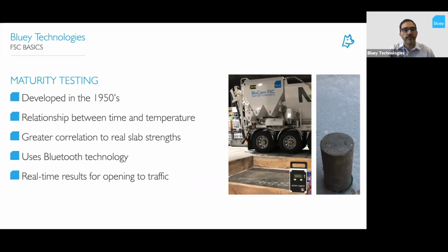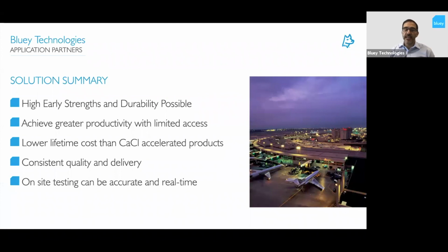So just in summary and finishing up, high early strengths and durability are possible, all in the one product. We can achieve greater productivity, even though we have limited access, by using fast set concrete and cement products. We have a lower lifetime cost than using a calcium chloride accelerated product, and we can now achieve very consistent quality and delivery, particularly with the backup of that on-site testing, which can be accurate and in real time. So a lot more reliability around fast set products, whether you're having them delivered by a weigh batching unit for a larger application, or even if you're just mixing a 20 kilo bag of a grout or a micro concrete, you've got a lot more reliability in those products.